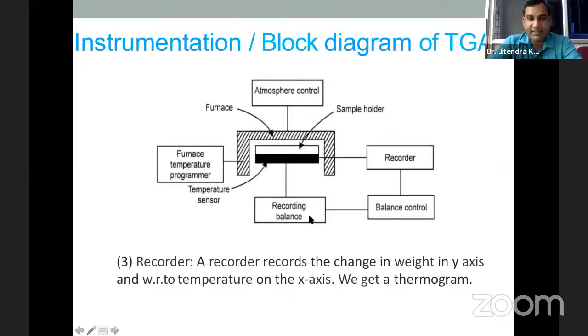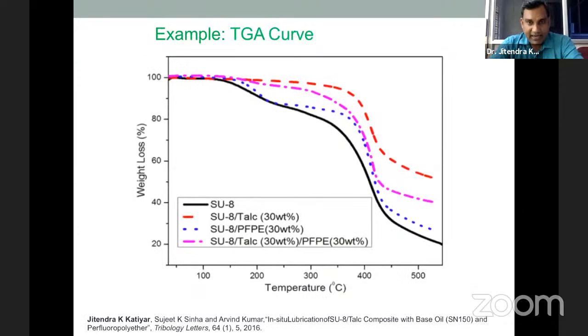If you want to pour only 1 milligram, and it is not 1 milligram, then the feedback system is provided. Again, you check it and pour 1 milligram of that particular compound. In this work I tested my samples by TGA, because SU8 is a polymer, and the temperature degradation of a polymer is very, very low.